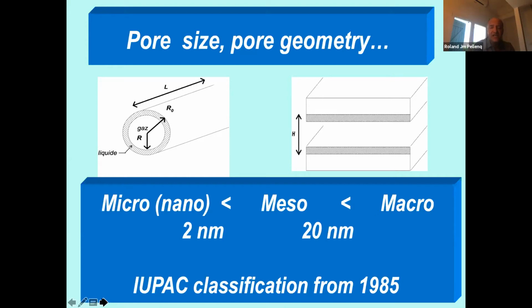And this is where this ranking of pore size actually comes from. It comes from a paper in 1985 from the IUPAC, the International Union of Chemistry, that produced this kind of rule, saying that micro is less than 2 nanometers, meso pores is less than 20 nanometers, and all above is called macro pores.